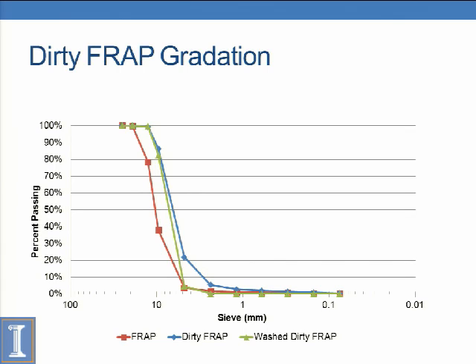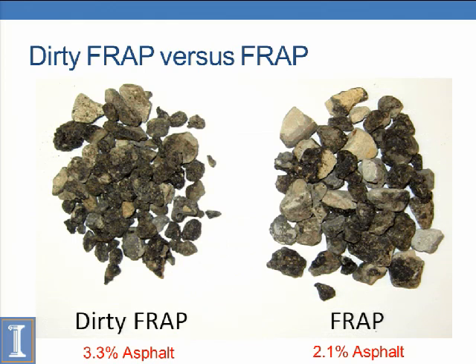The red line is our normal FRAP that we used in the previous slides, the previous mix design. And then this is our dirty FRAP, the blue line. So we can see it's a much higher content passing the number 4, which is why we call it dirty. It was an unwashed source, so there were a lot of fines. You can just see this is the normal FRAP we used, and this is the dirty FRAP. You can see a lot more smaller particles, also higher asphalt content. We had a 3.3% asphalt with this dirty FRAP, 2.1 with the typical FRAP we used.